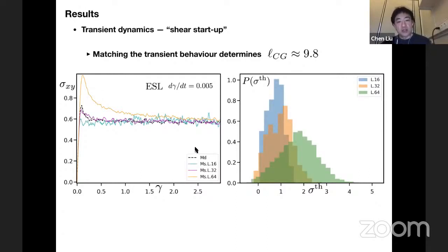This is due to the fact that when you have a smaller coarse-graining length scale, the local stress is much more overestimated. And if you have a very large coarse-graining length scale, what you measure as the local threshold is basically you're sampling the weakest one. So only with a reasonable coarse-graining length scale can you produce a reasonable, correct transient behavior in the shear startup. It's worth noting that this value of the coarse-graining length scale is also consistent with previous studies of the typical size of clusters of particles that undergo plastic events.